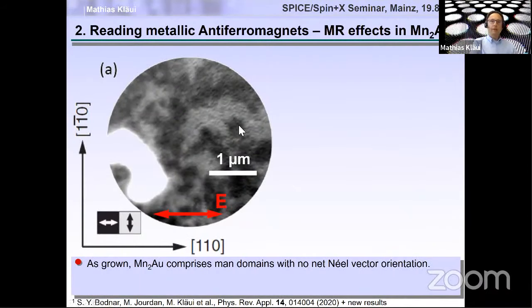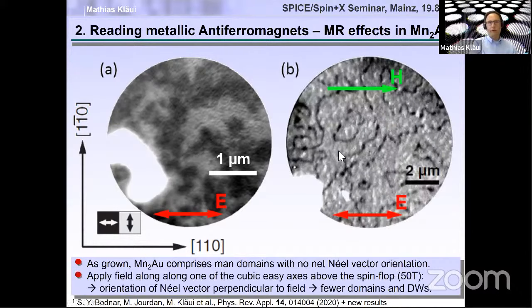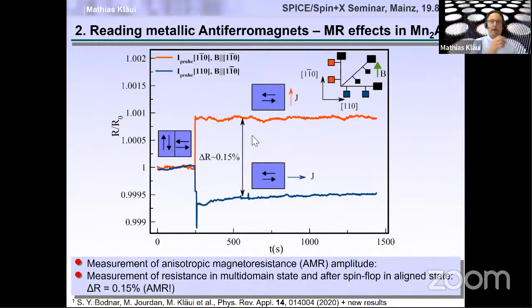So we have this multi-domain state where we see domains with different orientations. And we can then also go to a state, after applying a strong field, with a more or less aligned magnetization. And now we can measure AMR. AMR is interesting because it allows us to deduce the direction of the Néel vector, since there's a difference in the resistance for the case that the current is flowing perpendicular to the Néel vector, or along the Néel vector.